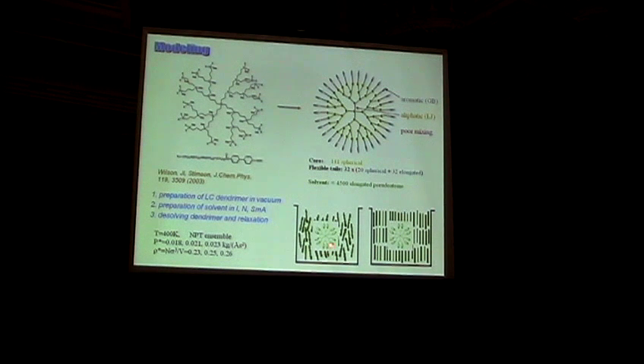And then we immerse the dendron inside and delete all the particles of the solvent that overlap with the dendron. After this, we performed NPT simulation to bring the density back and to bring the solvent back to the phase it has before the dendron was immersed.